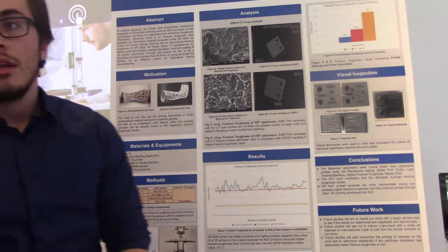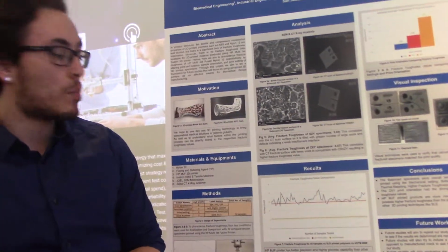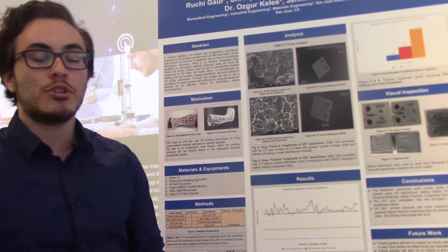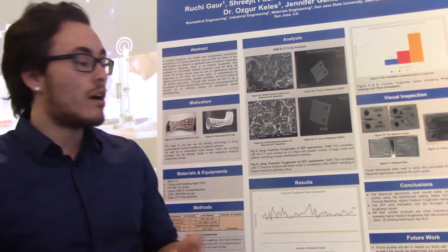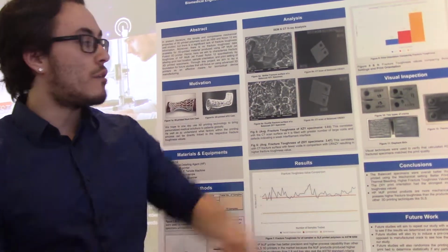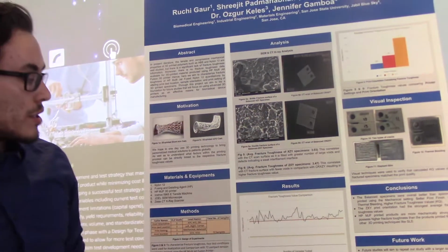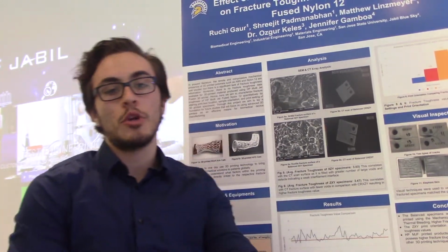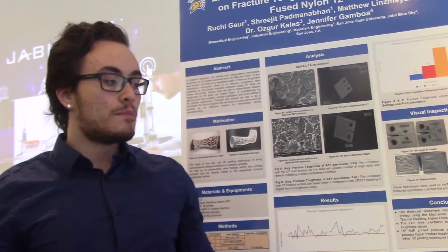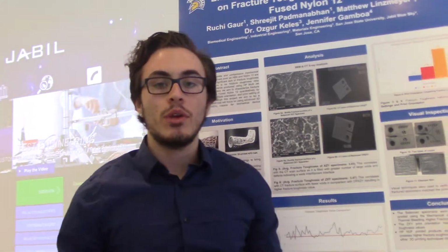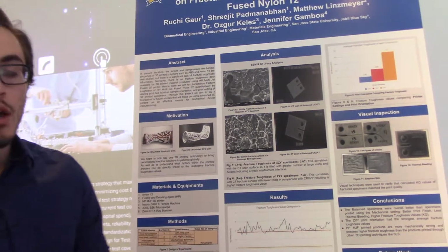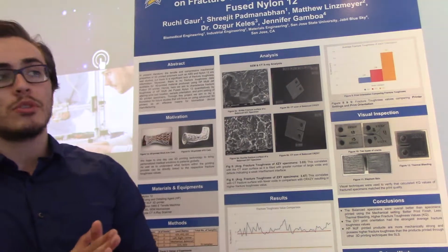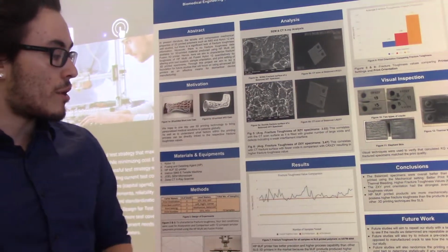So in conclusion, like I said before, balanced is overall the better print setting. It's slower, has better KQ values, less thermal bleeding, a better surface finish, and less of the 3 prong cracks. For our future work, we're going to try to continue this on, either pass it off to another senior project group, and continue to try to characterize these the best we can. With only 72 samples, we are only partially able to characterize it, but to truly characterize it, we're going to want about 300 samples or so, and just continue on from there.